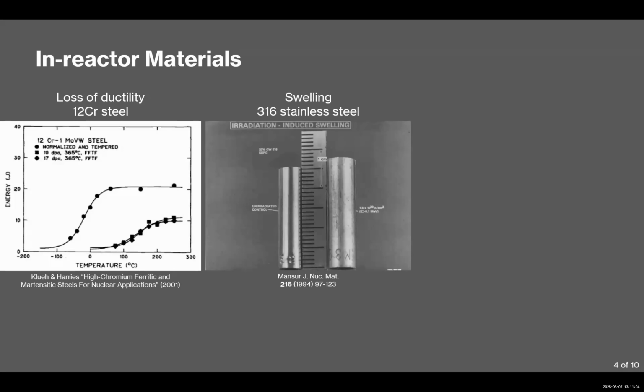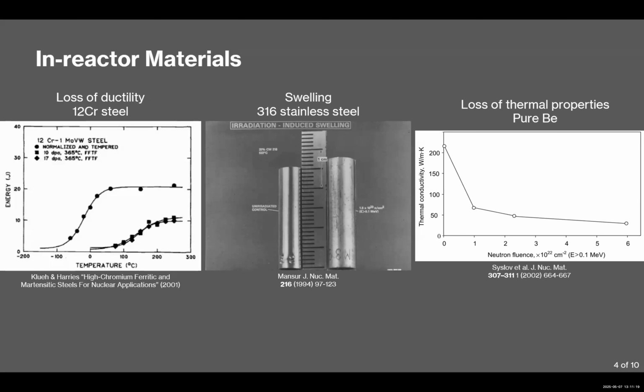You can also get swelling, which is a bit more intuitive. Your materials can grow as little gaps inside them coalesce. And if you've made things to a certain tolerance, which they definitely will be in these fusion devices, then this can just completely ruin that. You also get a loss of thermal properties as, like I was showing in the previous slide, your crystalline structure gets all messed up, and your electrons, which generally carry all of your heat and electricity in some cases, can't flow as well. In this case, we've got neutron dose on the x-axis and thermal conductivity on the y-axis, so you can see it drops by a factor of 4 plus over some exposure.